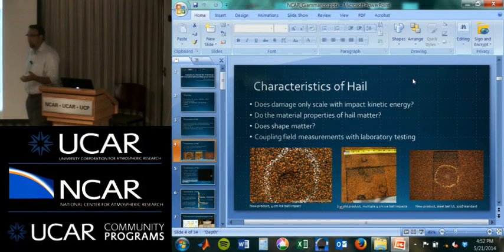Also, in a severe windblown case where you have a very shallow impact angle, the devices are virtually useless, because the structure of the impact is completely different, and the signal you get out of the piezo is very different. So the goal, if I can get somewhere in the 1/4 to 1/2 inch bin sizes, I would be very happy with that.